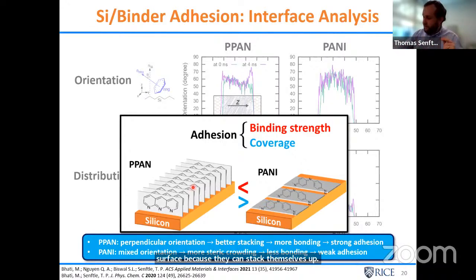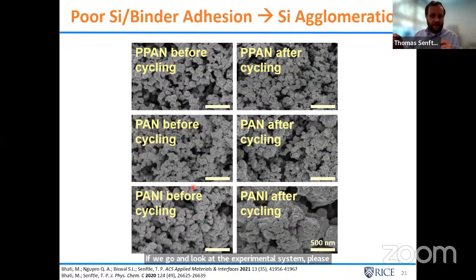If we go and look at the experimental system, these are micrographs, again, from our experimental collaborators, the Biswal group, and we look at the structure of the silicon before and after cycling, we see that the p-pan and the pan, which bound with the bulk fairly strong to the interface, adhered well to the interface, they maintain their structure. So the silicon is not agglomerating into these larger particles, so we're not losing the active surface area. Whereas polyaniline, we get a significant agglomeration because of that weaker binding, okay?